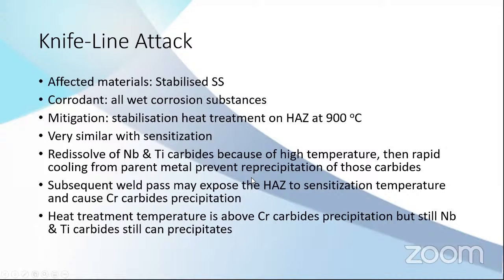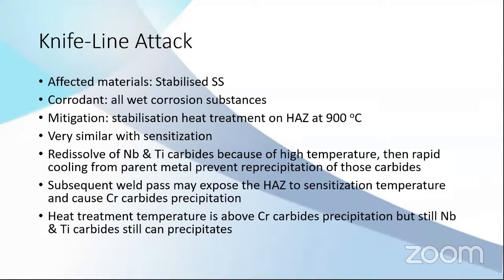So the problem is that the chromium carbides form at a temperature lower than 900. So when it is exposed to that temperature below 900, the niobium and titanium still cannot take the carbon because it's not the temperature where they can take the carbon. The problem: then chromium takes the carbons and it gets sensitization. So it's the same thing as sensitization, but it just happens on the stabilized stainless steel.